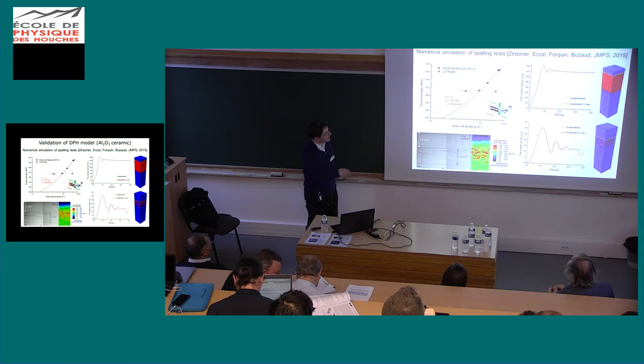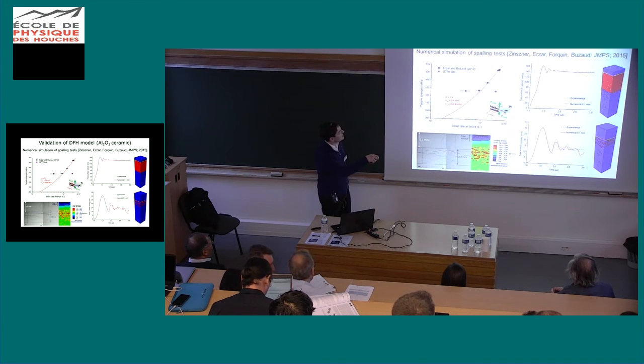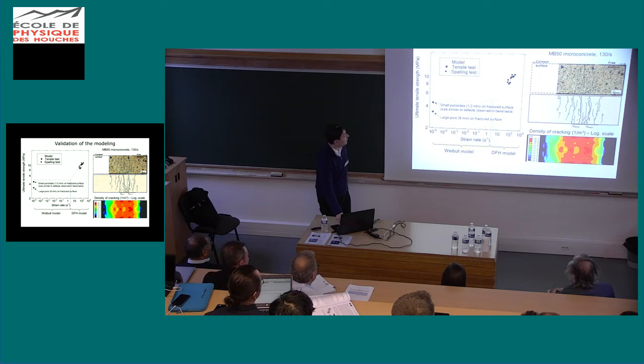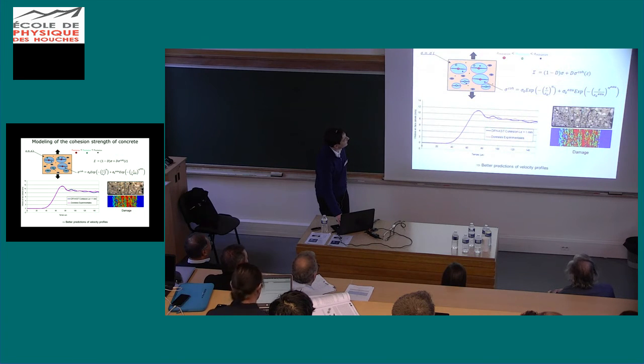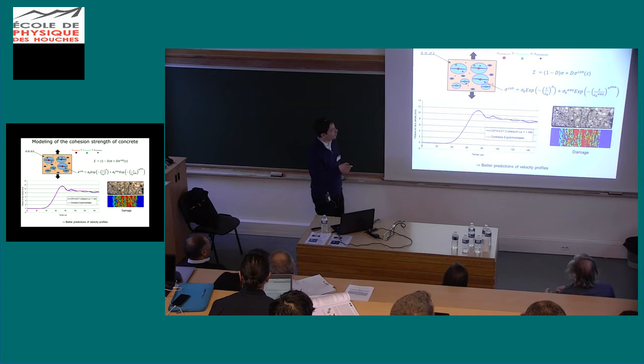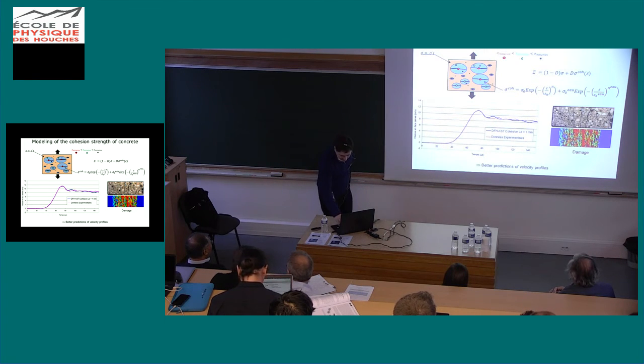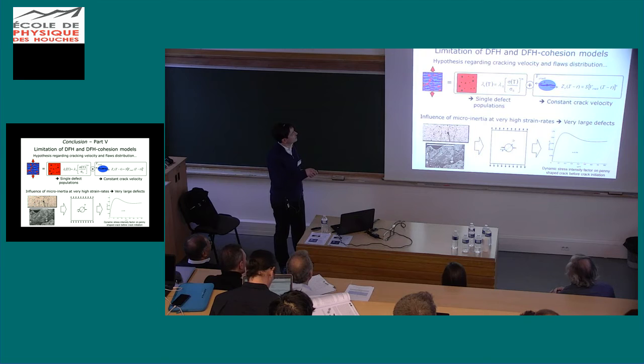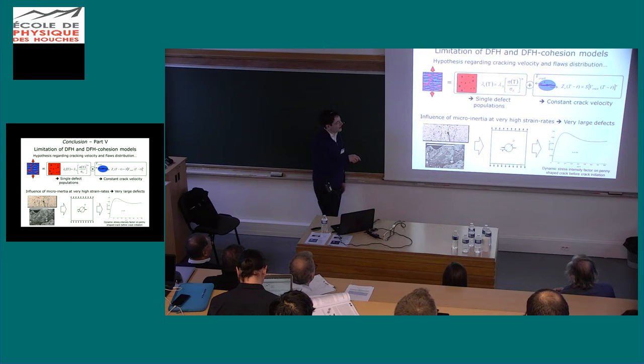So we can see here the velocity profile predicted by the numerical modeling and compared to the experimental results. And here you can see the strength increase with strain rate. Here the same kind of validation was performed with microconcrete, as you can see. And we added an extension to this model to represent the cohesion strength for concrete. Okay, so there are several limitations. The main limitations are, of course, related to the assumptions that we use here: a power law function of the applied stress for the critical cracking density, and we assume a constant crack velocity. And we neglect microinertia at the micro scale, but I won't go into these details.